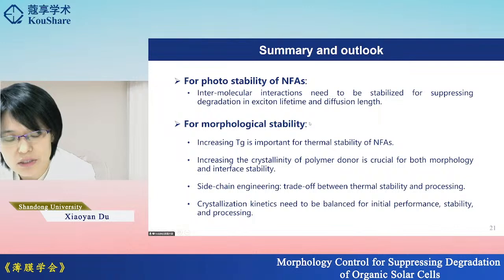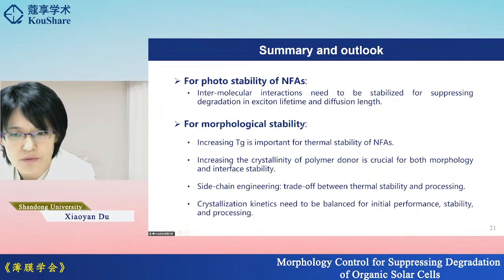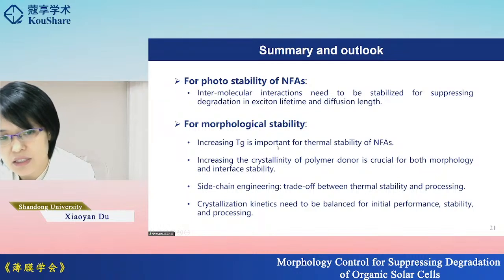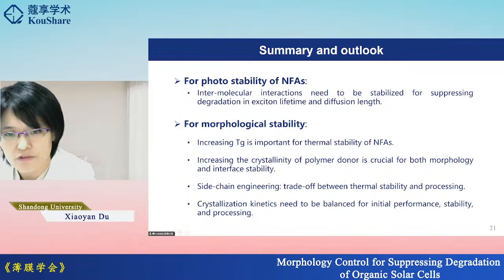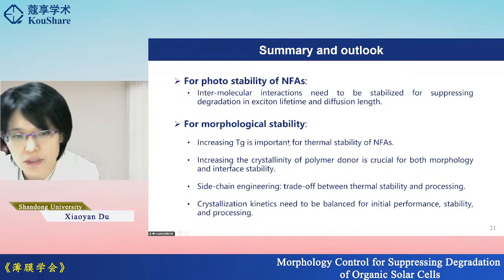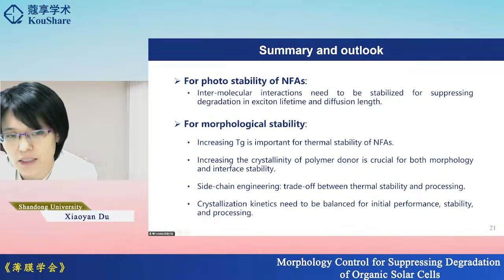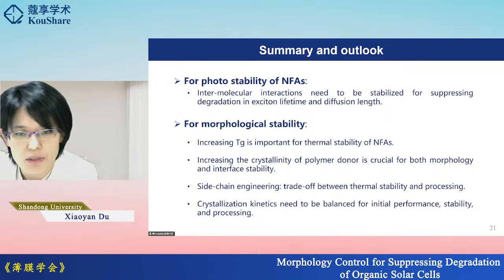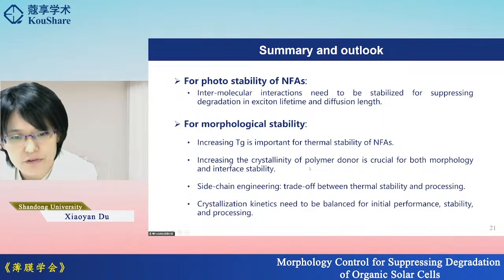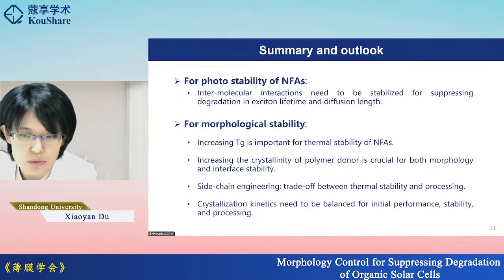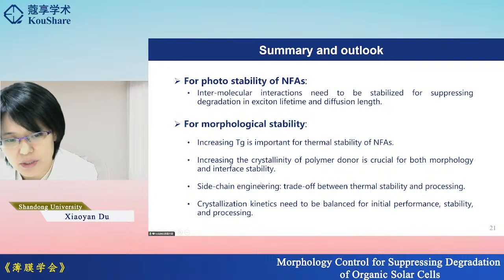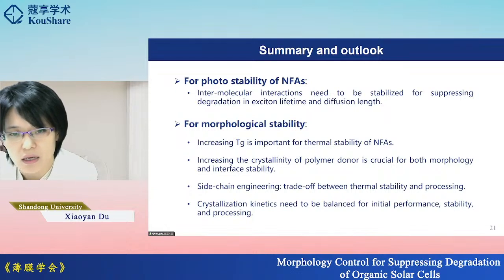And for the morphological stability, the result shows that for most of the non-fullerene acceptors, the Tg is relatively low in terms of thermal stability. But we also notice that there are more reports about the oligomer non-fullerene acceptors, which increase the Tg and also showed a very promising thermal stability. And as for the polymer, the crystallinity is crucial for both the morphology and interface stability. For the side chain engineering, we need to consider the trade-offs between stability requirements and processing towards upscaling.